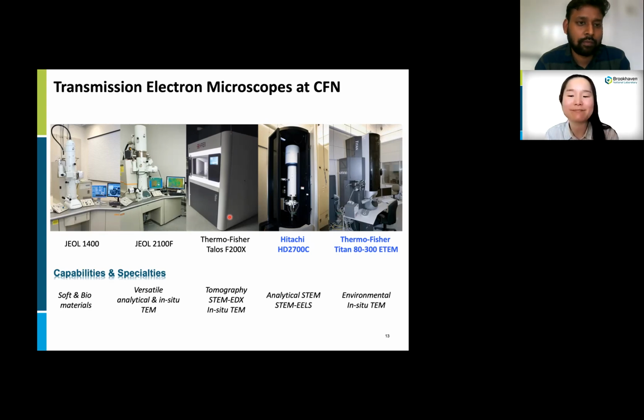Hitachi HD2700C is a dedicated STEM with EDX and EELS, and also it is equipped with a probe Cs corrector, which corrects the errors from electromagnetic lenses. As a result, we can make a very small electron probe, and we can improve spatial resolution in